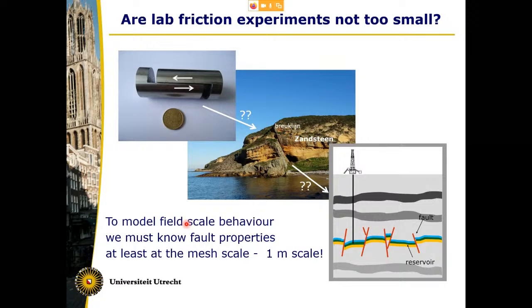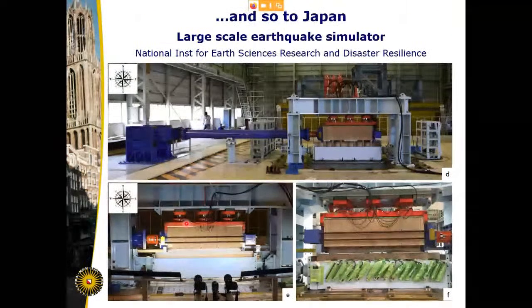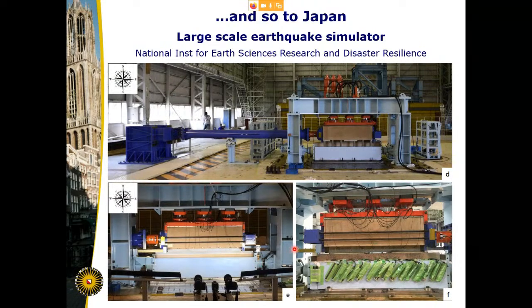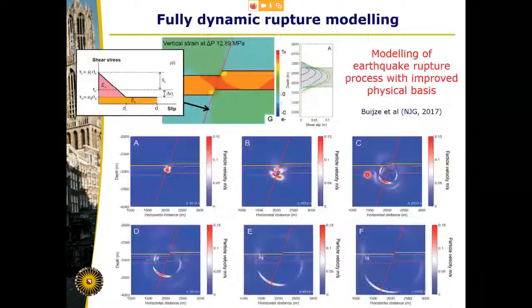Does size matter? I have to cut corners here, otherwise I'm running out of time and Hadi is going to chop me off. To find out whether these tiny little samples actually produce reasonable results for friction, we did meter scale experiments at an earthquake science laboratory in Japan. And I won't show you the results. Take it from me. To our astonishment, for the rate and state dependent friction behavior of these materials, we got exactly the same results in this monster machine with 1.5 meter size sandstone blocks sliding across each other as we did with the 5 centimeter assembly in the lab in Utrecht.